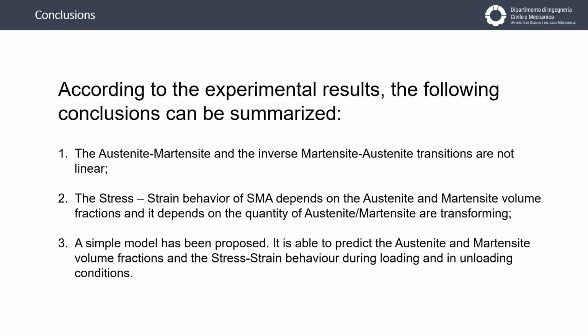In conclusion, we proposed an easy model able to calculate the quantity of austenite and martensite during the loading and unloading process, and it's able to predict the stress-strain behavior of shape memory alloys, taking into account the real quantity of austenite and martensite present in the material. This model is easy to implement in commercial software, but takes into account just materials characterized by the presence of two phases, austenite and martensite, without any other phases. But the extension of this model, I think, is not so hard to formulate. Thank you very much.